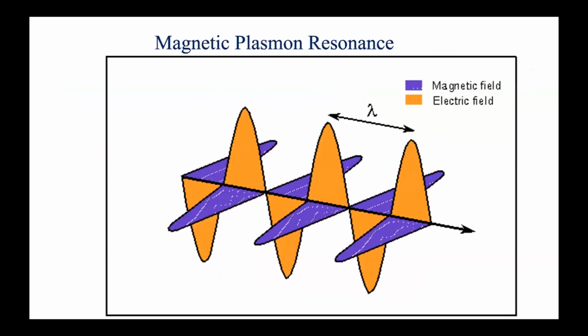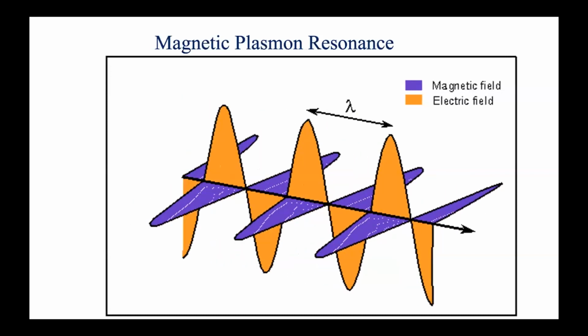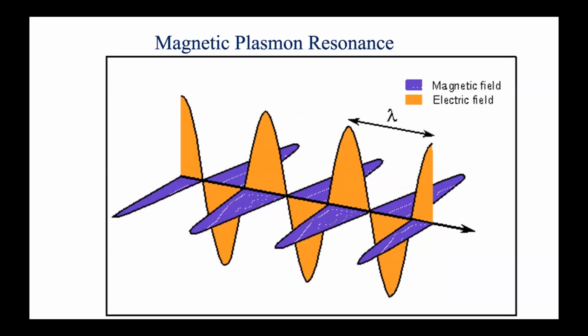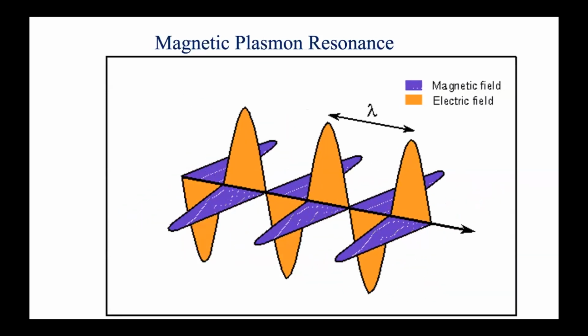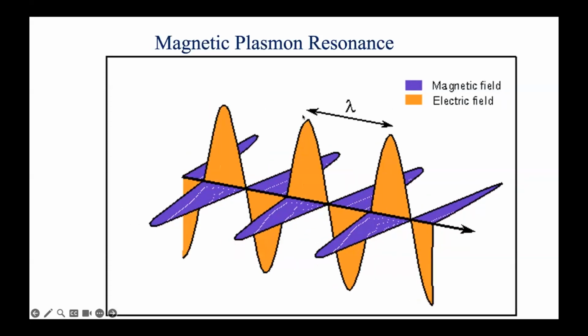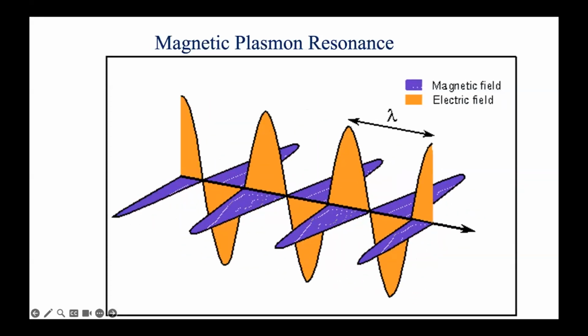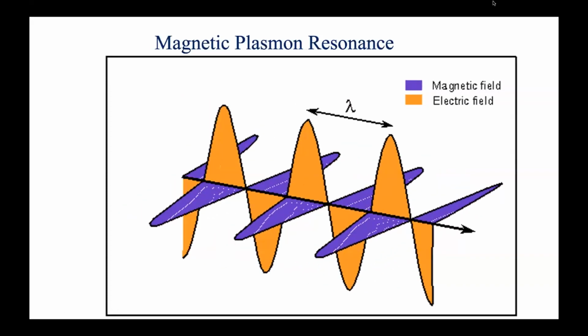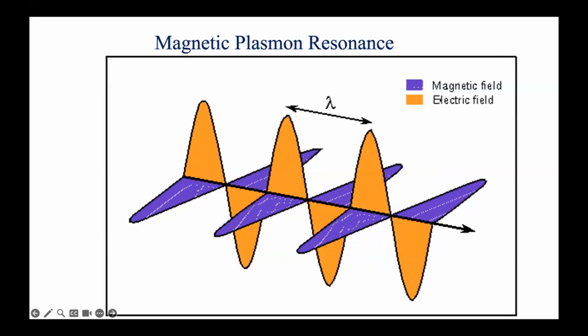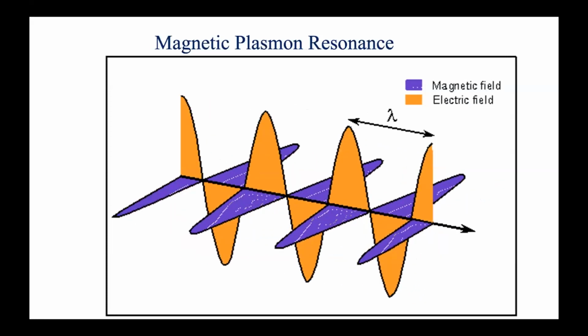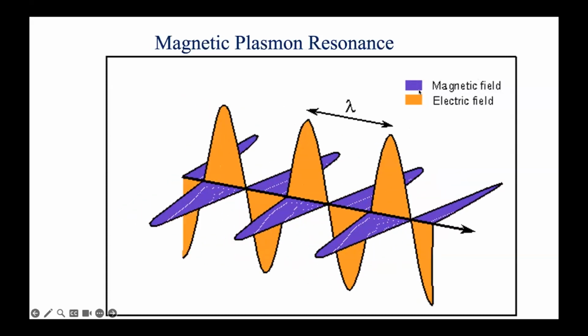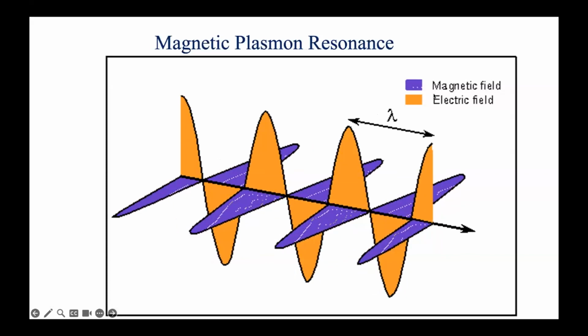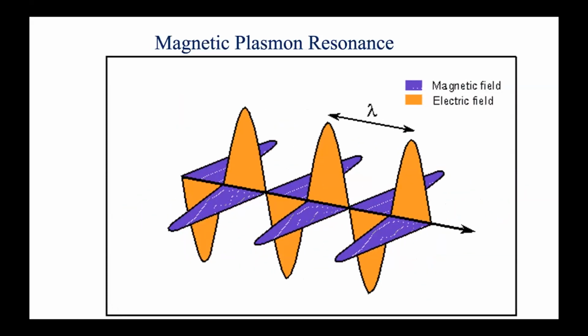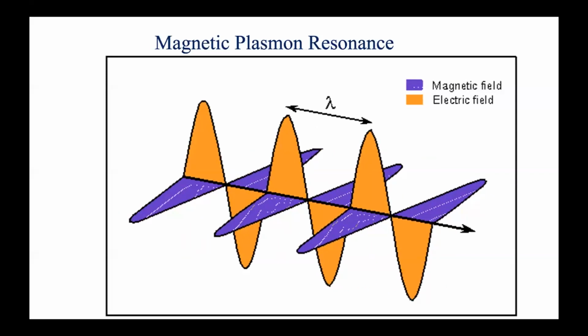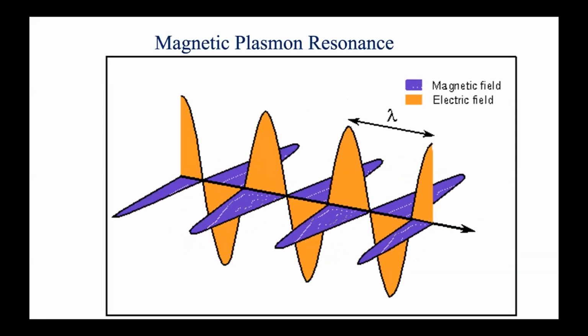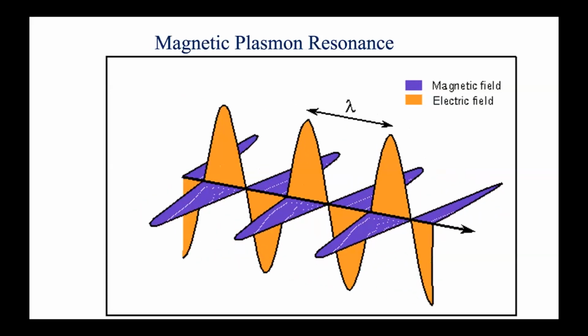The motivation for incorporating the magneto plasmonic nanoparticle is that previous plasmon enhanced photovoltaic devices were based on the interaction of free and bound electrons with an applied electric field. But interactions with the magnetic field, that means the B component, of an incoming electromagnetic wave were not considered. So as I've said, we propose that the use of magnetoplasmonic particles should lead to the enhancement and tuning of the absorption of sunlight to match the band gap of the photoactive layer.